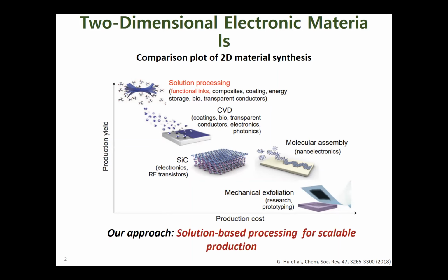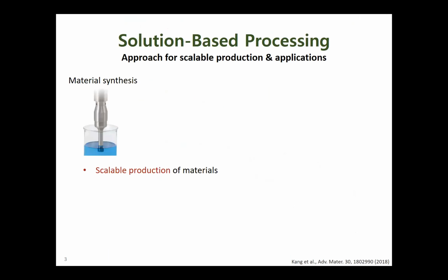Solution processing has been considered a promising route for scalable production at low cost. This method generally relies on the exfoliation of bulk crystal in a specific solvent by mechanical energy transfer that overcomes the van der Waals interaction within layered material.